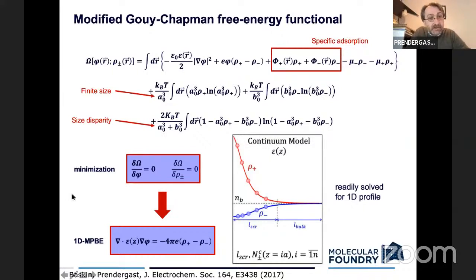Okay, so with this free energy, you can minimize that functional to find the optimum value, or the stationary point, with respect to the potential and with respect to the density profiles of the species you care about. We only solve this in one dimension, and we end up with this modified Poisson-Boltzmann equation, which looks very similar to the normal relationship you expect between the potential and the density, except now it has the dielectric function in there as well. And what you get when you do the calculations are these kinds of profiles of ions as a function of distance from the interface. So there'll be a screening region and then a bulk region.